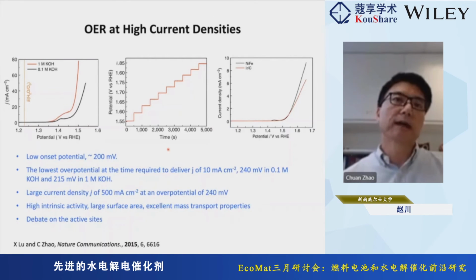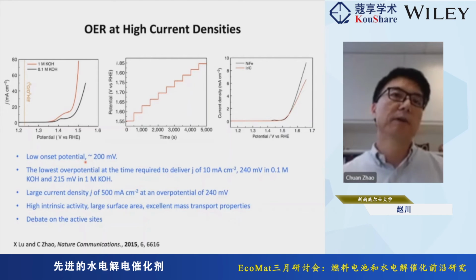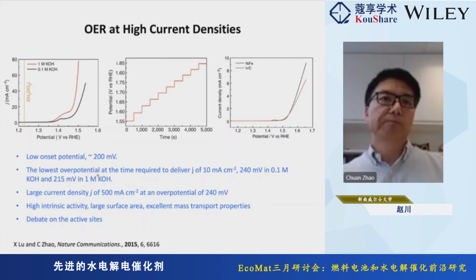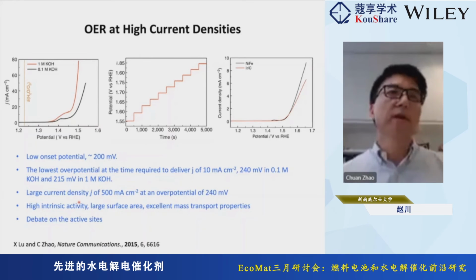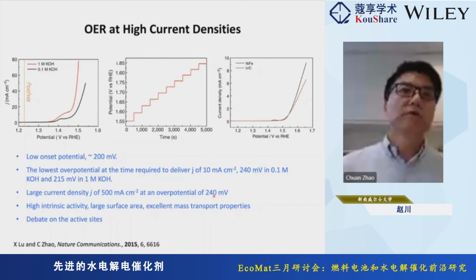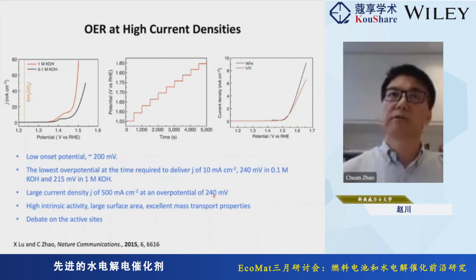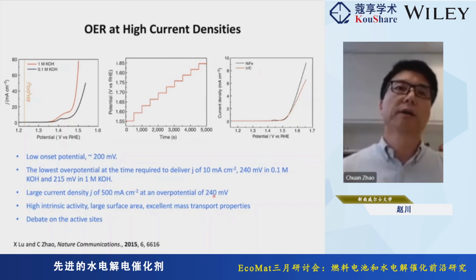Overall, we have a freestanding electrode with very high surface area and very good mass transport properties. The electrode had extraordinary performance and gave a very low onset potential of around 200 millivolts, which is the lowest overpotential reported at the time to deliver the OER. More importantly, the electrode performs very well at large current densities. For example, at 500 milliamps per square centimeter, we have an overpotential of only 240 millivolts. We attribute this high performance to the high intrinsic activity of the nickel iron itself, but also the large surface area and the excellent transport properties. Particularly at these large current densities, we get good transport of the reactants to the electrode surface, and the gas bubbles generated can be quickly released from the electrode.